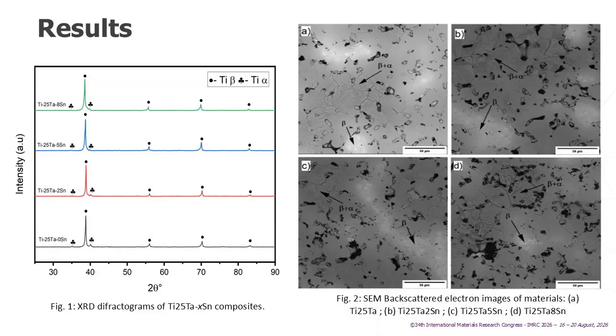Image A shows two types of microstructures in the titanium 25 tantalum alloys. The bright areas indicate the presence of tantalum, which stabilizes the beta phase. In other areas, a beta plus alpha microstructure is evident, which forms due to the beta to alpha diffusive transformation.